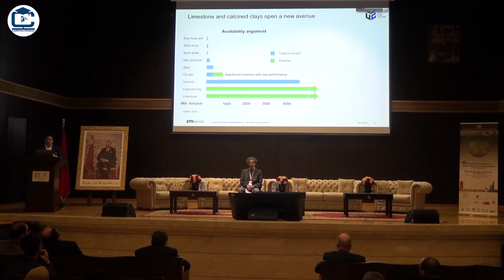So the first argument for going then for limestone and calcined clays is definitely an availability one. We haven't been able to increase our replacement level of clinker by supplementary cementitious materials because we don't have enough stuff. If you compare the demand of cement today with the availability of other materials, you can see that there is no way to replace, let's say, 50%. And it's only calcined clay and limestone, these 2 materials, that can really change the situation because they are available in quantity and, more importantly, in the places where we need cement and concrete production, which is in the emerging economies.